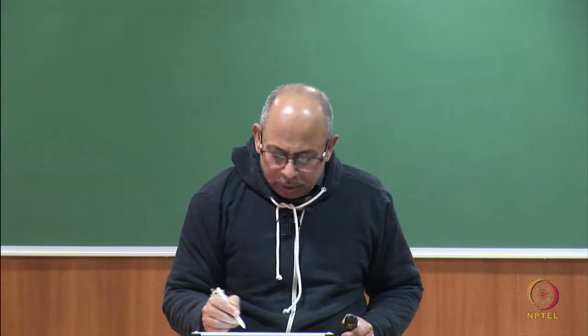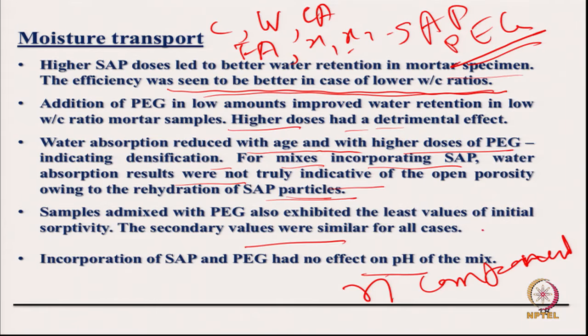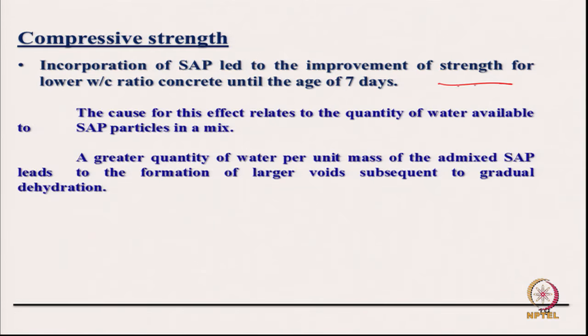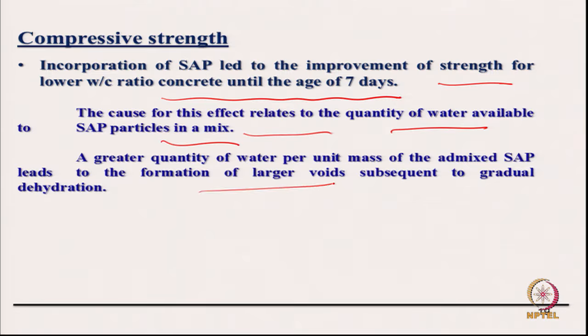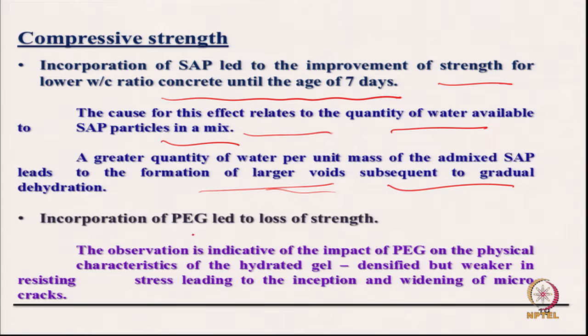The pH of the mix does not change, because that has something to do with durability, initial absorption, etc. So, some durability properties show proper improvement. There is improvement in strength for lower water cement ratio at 7 days, beyond that it reduces. The cause for this effect relates to the quantity of water available in the SAP particles mixed. A greater quantity of water per unit mass of the admixed SAP leads to formation of larger voids. These are details, but I think I have made my point already, that incorporation causes some loss of strength in the long run.